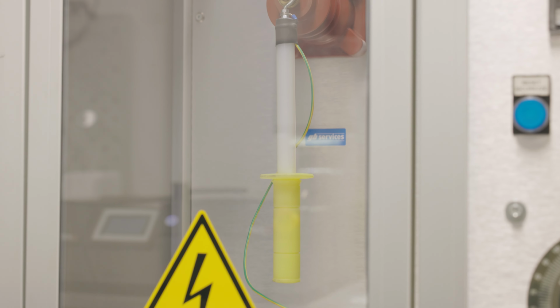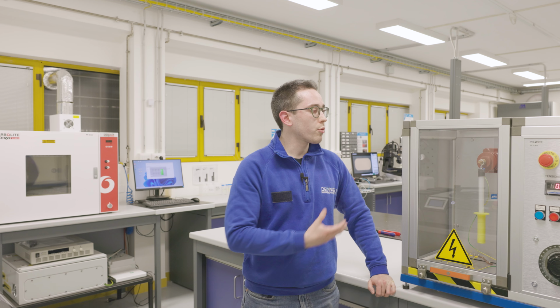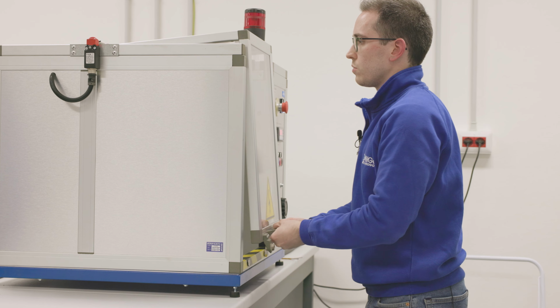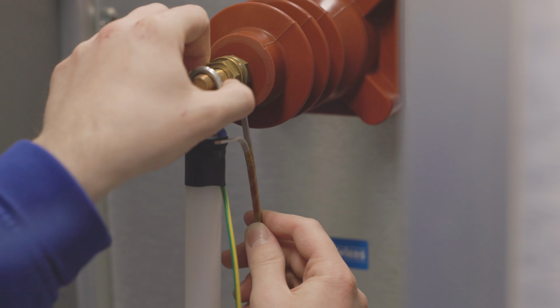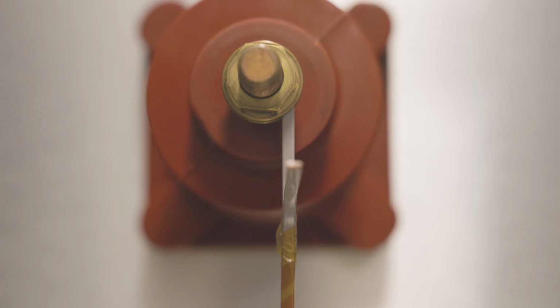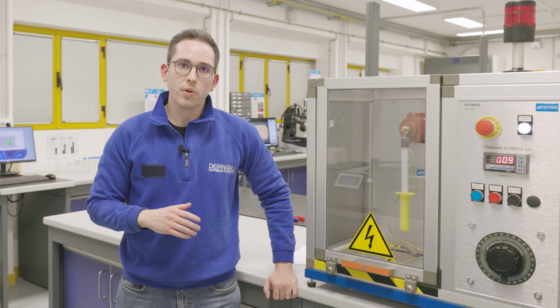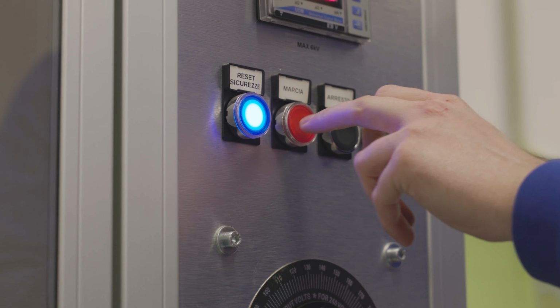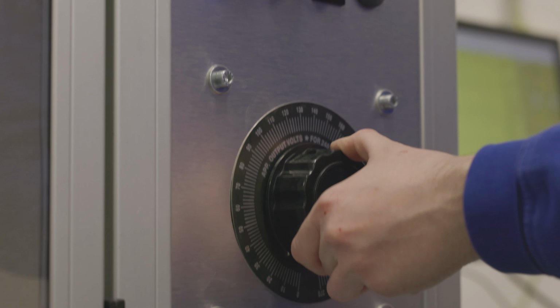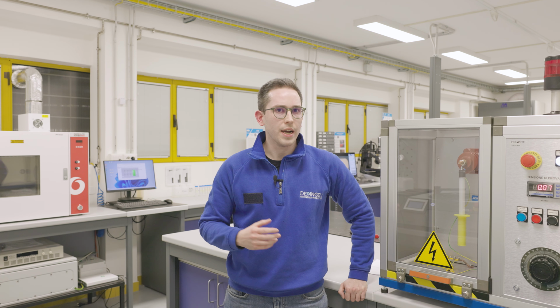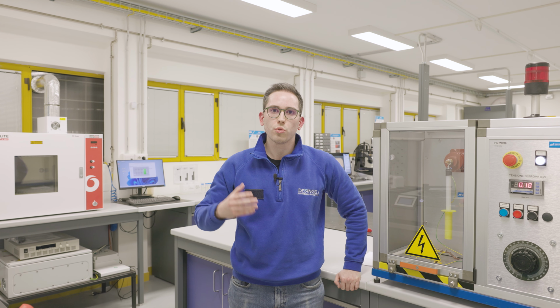And finally, we reach the core of our automotive validation. Here we can perform partial discharge testing in order to verify our insulation limits and the presence of defects in our enamel. Coupled with this, we can conduct voltage endurance tests, up to 6 samples in parallel using pulse signals. This allows us to simulate real inverter conditions in air and in oil, reaching temperatures up to 220 degrees. From chemical analysis to electrical testing, we are able to provide the complete characterization to drive the future of automotive.